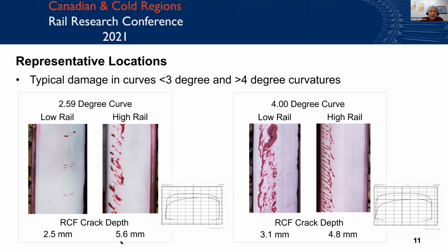That's very significant. Shift that over to a 4 degree curve, and this is a typical rail that we saw there. So even more plastic metal flow compared to the 2.6 degree curve. And again, this is the same rail age. This is a 1985 Algoma rail for both of them. So this is the type of rail that is very, very similar to the type of rail that led to the derailment. So I invite you to look at the paper and the results, and there's a lot more detail in that.